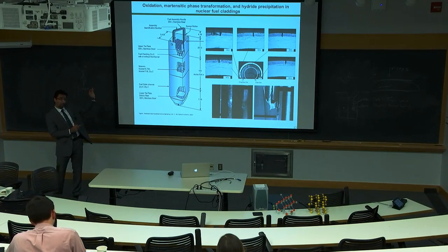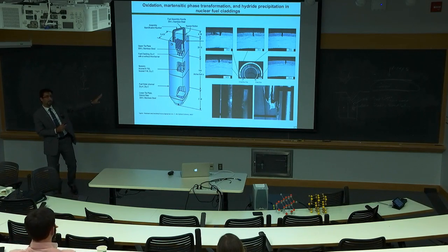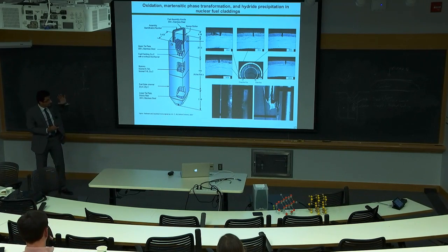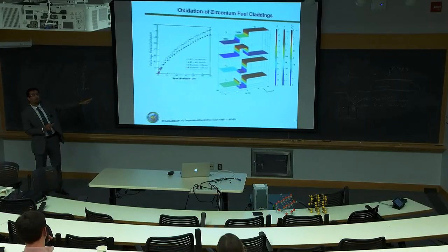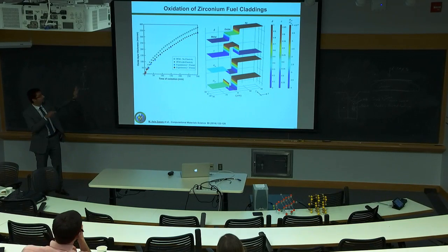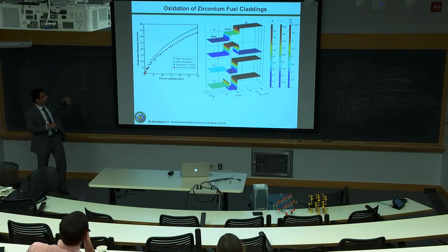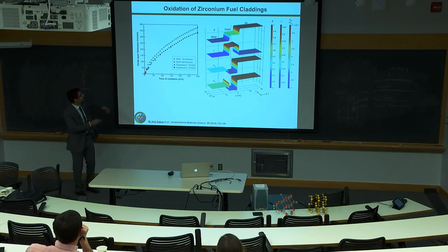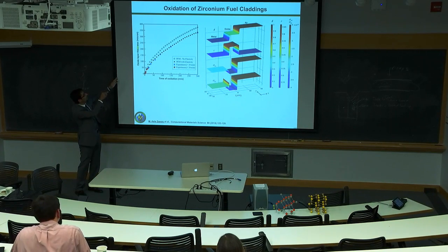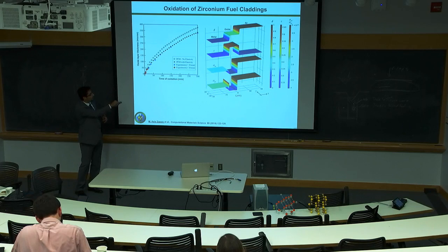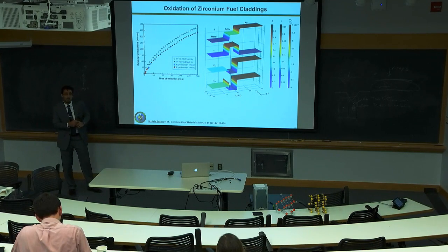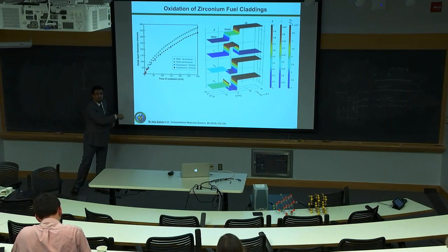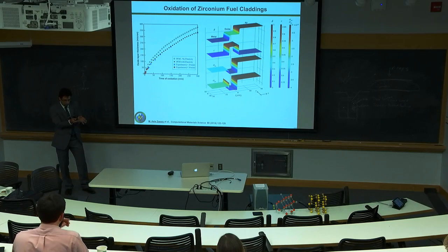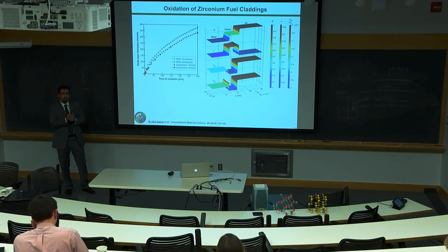I'm not going to talk about all of those. I'm going to emphasize the phase transformation part that we have developed. For example, a model for oxidation of metals, which we applied to zirconium. What it can predict is how thick that layer will become after a given time of oxidation at different temperatures. It also predicts the stresses generated. Okay, so it is completely coupled to the constitutive equations of solid mechanics.